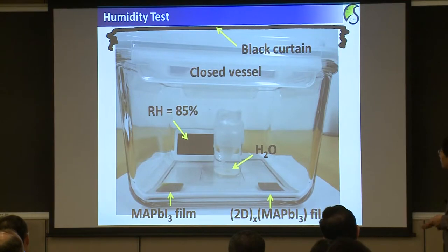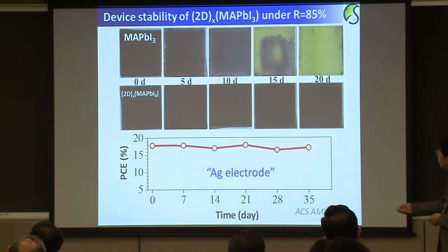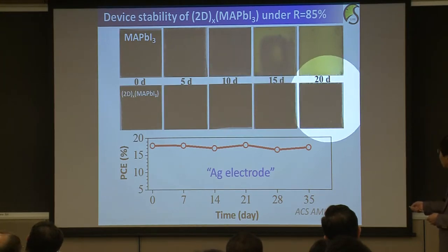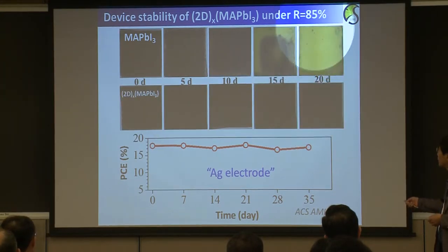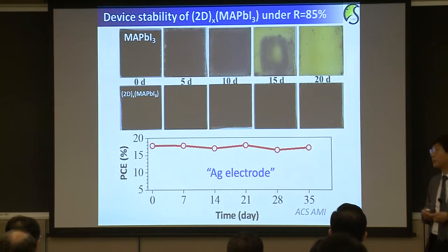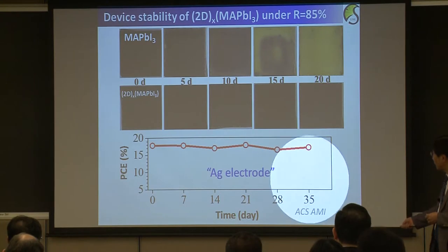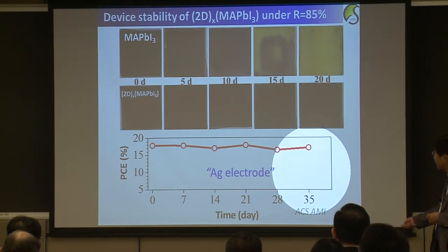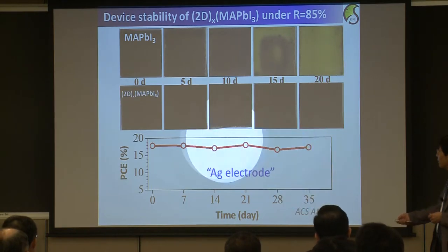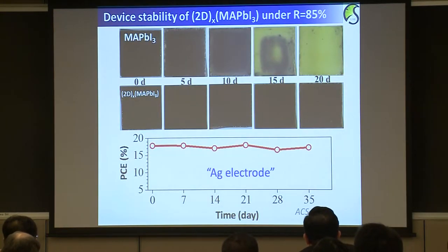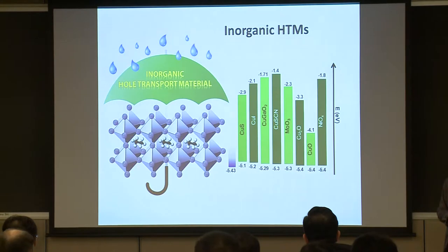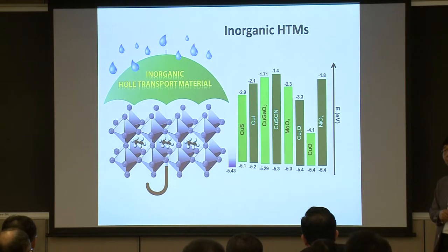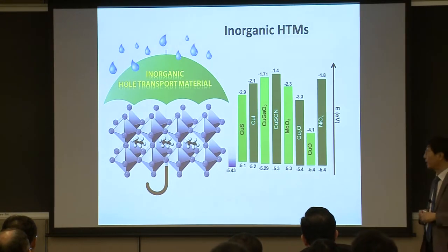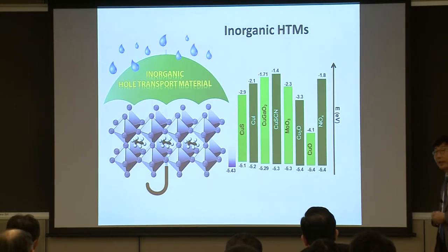And also we tested the humidity stability. And the two-dimensional structure is much better in terms of moisture stability compared to without the two-dimensional structure. So even, for instance, with silver electrode here, we can get a 35 days stable perovskite solar cell by inserting a two-dimensional perovskite in the MAPbI3. This may be due to the suppression of iodide migration. And then we inhibit some oxidation of the Ag electrode in order not to form AgI.